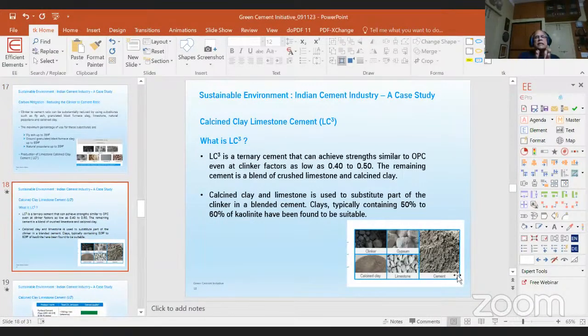Now LC3 is a ternary cement that can achieve the required strength like OPC. That's important. Even at the clinker factors as low as 0.4 to 0.5. That means per ton of cement, just 40% of clinker is required. The remaining is a blend of crushed limestone and calcined clay.